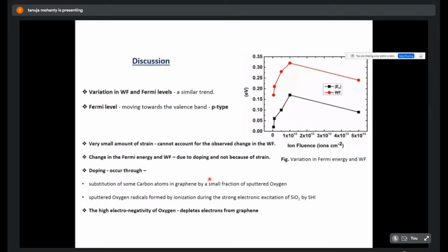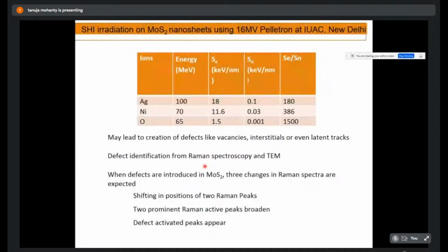So that helps in the doping occurring through the substitution of the carbon atom in the graphene by a small fraction of sputtered oxygen from the SiO2, and this sputtered oxygen radicals formed by ionization during strong electronic excitation. And next I will just tell about some things on molybdenum disulfide.